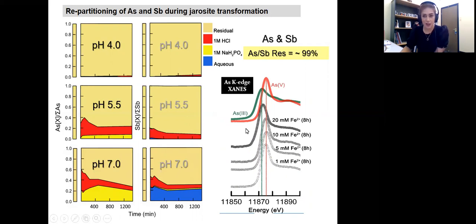And very interestingly, we saw that with our arsenic, we have a little bit of shift in the edge of arsenic 5 towards the edge of arsenic 3, which shows that we probably have some electron transfer from arsenic 5 to arsenic 3, and we have some reduction. So a proportion of that surface adsorbed arsenic that is now at the surface of goethite could be arsenic 3.